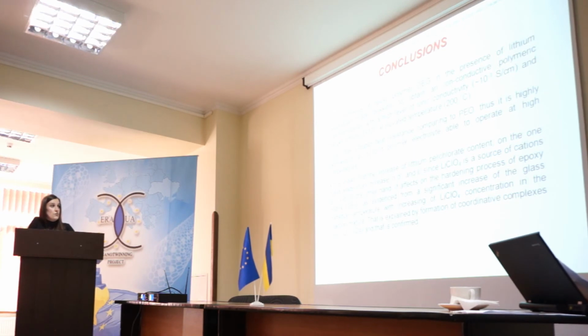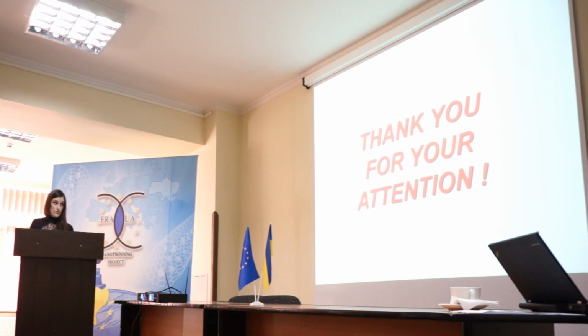It shows that the increase of lithium perchlorate content, on the one hand, leads to an increase in permittivity and conductivity, since salt is the source of lithium cations, and on the other hand, it affects the hardening process of the epoxy matrix, as evidenced by a significant increase of the glass transition temperature with increasing salt content in the reaction mixture. That is explained by formation of a coordinating complex, and that is confirmed. Thank you for your attention.